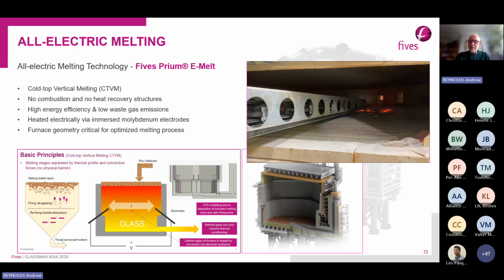The furnaces operate in a slightly different way. The melting processes occur vertically, and we put the raw materials onto the top surface of the melt. So we call these vertical melters. The raw materials go on the top, and the fully melted, refined product comes from the bottom of the unit in what we call the throat. These furnaces don't have any combustion. They don't have any heat recovery structures. So structurally, they're much smaller, and they're very energy efficient, certainly in terms of energy per unit of glass produced.